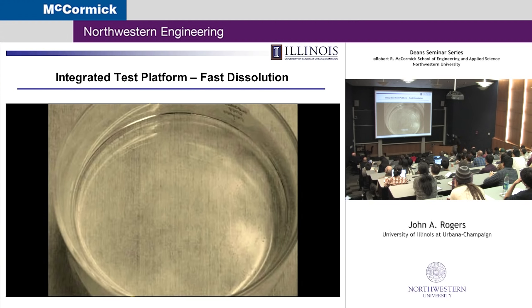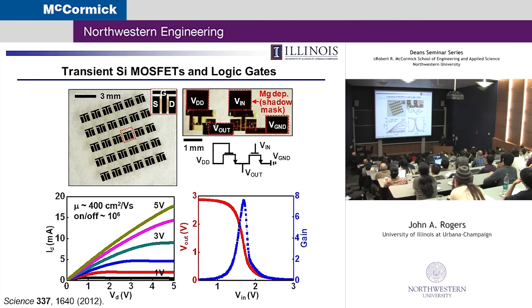In this case, it's essentially amorphous, so it dissolves very quickly. When it dissolves, it causes the magnesium traces to fragment. They dissolve themselves to magnesium hydroxide in a few hours, and you'll see that in time lapse. Eventually, the magnesium is completely gone. The silicon is not, but you can't see it. It's much too thin and much too small to be visible at this scale, but it will dissolve over a period of a couple of weeks. And so it's completely gone.